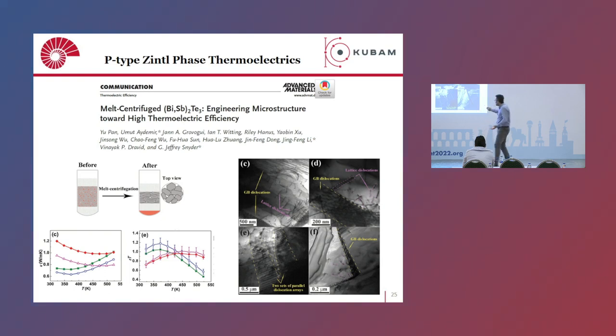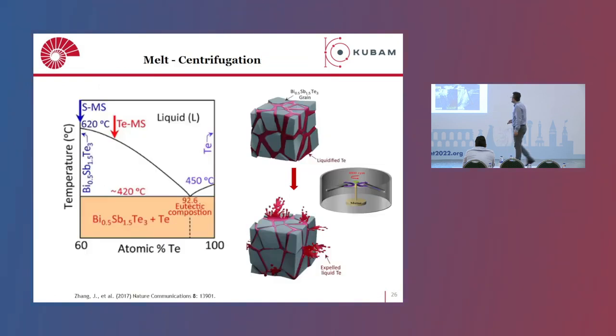And we saw that in bismuth antimony telluride, you can have a lot of ordered grain boundaries, and within the grains, we have a lot of lattice dislocations. You can see them as lattice dislocation networks or regular lattice dislocations. This lowered the thermal conductivity substantially. This is the non-centrifuged material, and you can see that you can lower the thermal conductivity to 50%, and ZT can also be improved a lot.